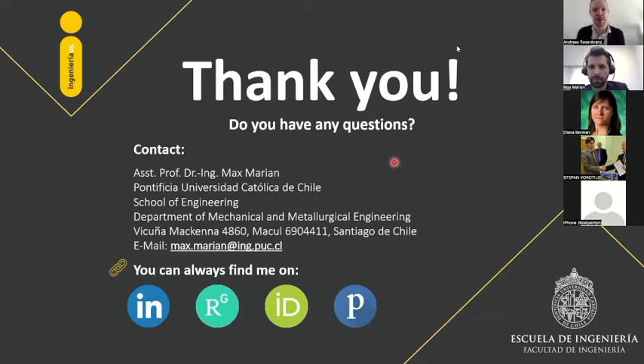So the first one is, did you deposit MXenes from water solutions, and which etching conditions have you used for MXenes? No, we drop casted the MXenes, at least for the bearing applications, from acetone, and for the nanogenerators we used isopropyl alcohol because water is a little bit aggressive for the polymeric PTFE substrate. And the etching conditions were the very classical etching strategy of the MXenes using acid. Exactly, the MXenes were either etched with HF or with lithium fluoride and HCl, the standard methods, the harsh one and the milder one.